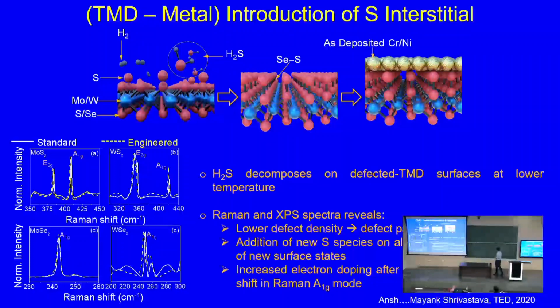Now coming to the TMD, what we had to do was introduce sulfur interstitials and a certain metal. We developed this method where H2S, which is also used as a precursor for growing MoS2 or WS2, breaks at the surface of MoS2 or WS2 at a moderate temperature. When it breaks, the sulfur stays back and the hydrogen evaporates. Then you can deposit metal. The sulfur goes in as interstitial and the metal captures the sulfur. So even if you do some cleaning afterwards, the sulfur is under the metal.